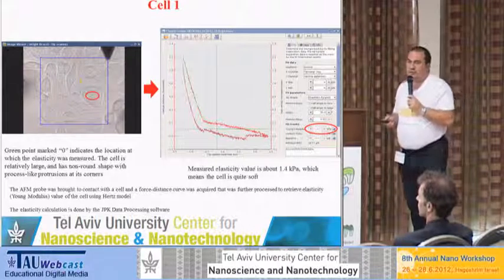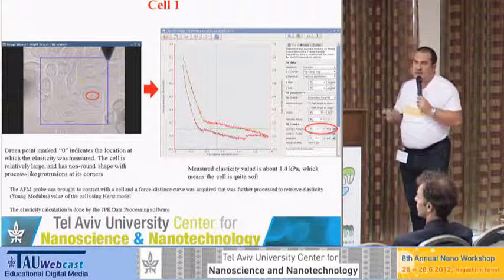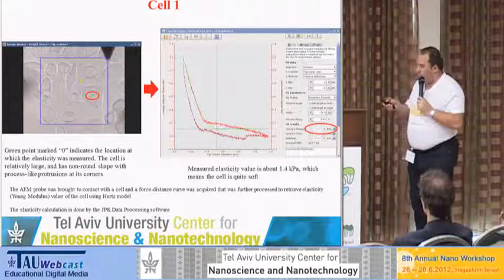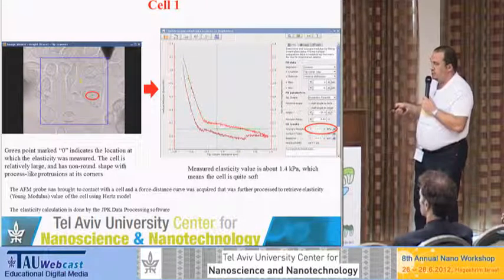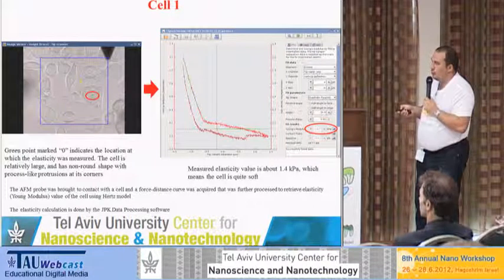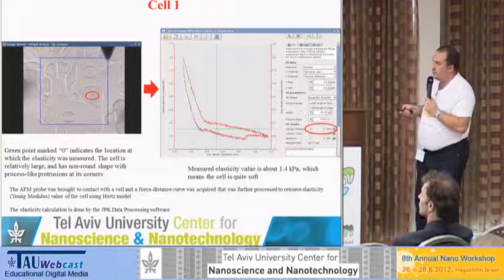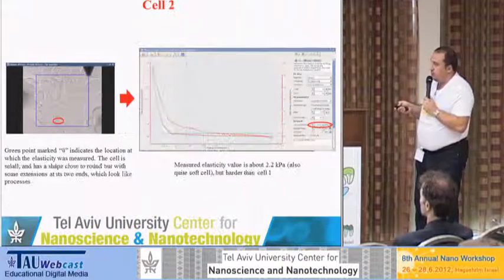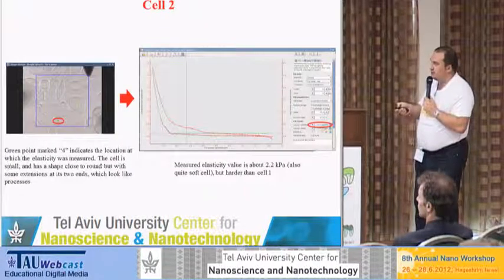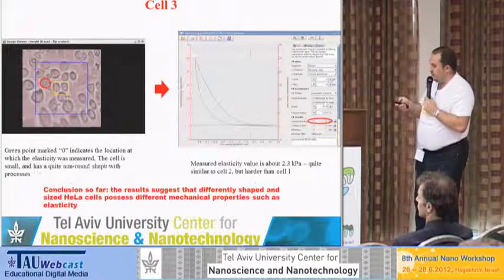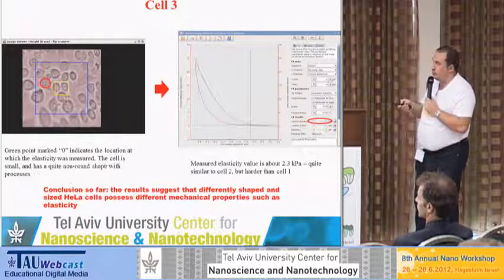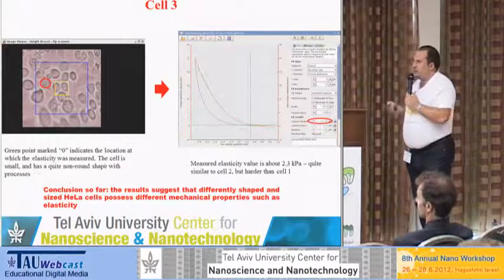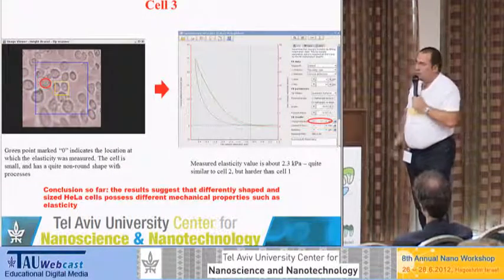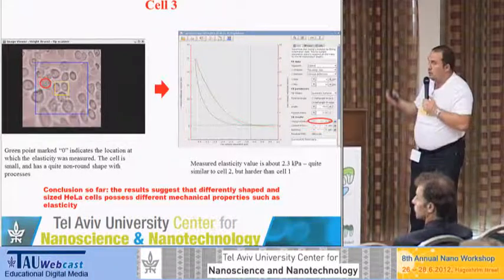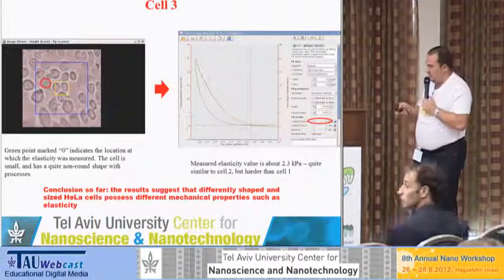Initially, we just took cancer cells of different shapes and sizes, and saw that first of all we really measured the elasticity, the Young modulus. You can see here for the big cell it's about 1.4 kilopascal, and for other cells like this cell it's 2.2. Another cell gave 2.3, which are smaller cells. So it's not very statistical, of course. So we took more curves, but the main